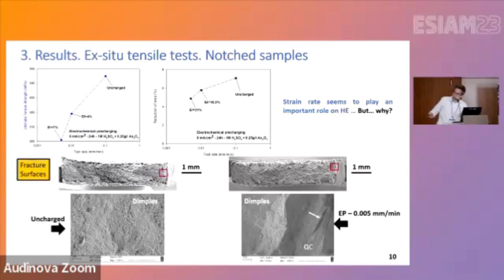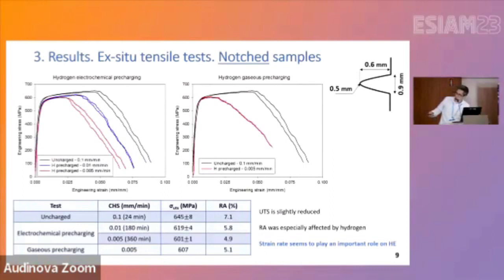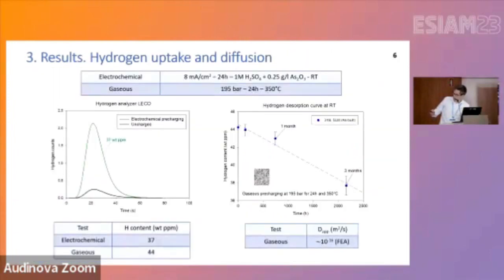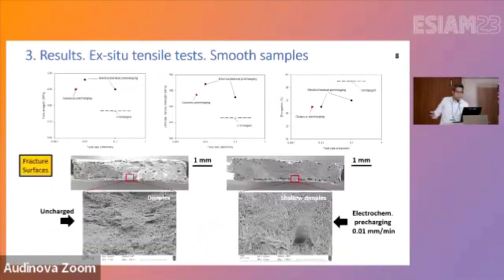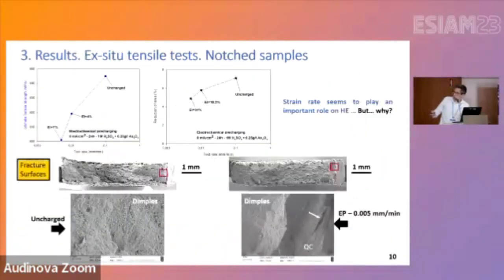And here, regarding the fracture surfaces, we can see dimples, microvoid coalescence in the uncharged condition. However, after hydrogen precharging, we have observed dimples together with local quasi-cleavages and secondary cracks, which contribute to justify this behavior. So the point is, the strain rate seems to play an important role on hydrogen embrittlement, but why? Because as we can see here, our test lasts from 24 minutes to 6 hours. However, it seems, according to this behavior, hydrogen needs around 1 or 3 months to diffuse. So what is happening in the microstructure to explain this behavior?